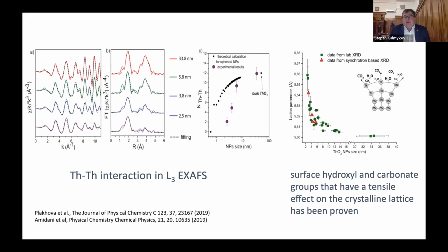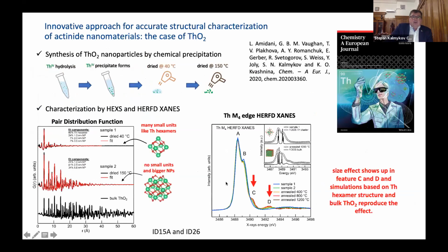And also, maybe not surprisingly, what we observed from many independent measurements is that in this nanoparticle region, 2 to 10 nanometers, we have changes of the lattice parameter that are due again to the number of surface atoms, which is important when we are speaking about very small particles. Certainly the surface hydroxyl and carbonate groups also have some tensile effects. So changing the lattice parameter is important again for this nano region.